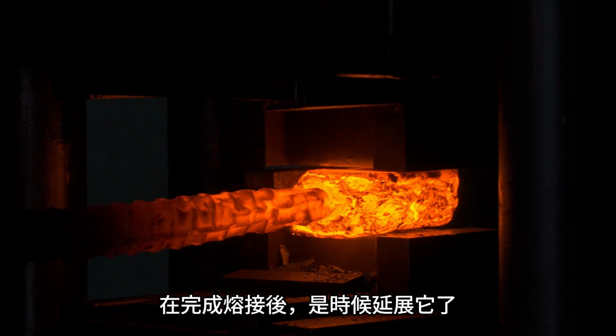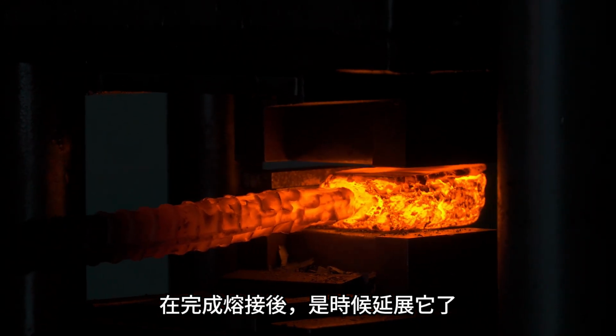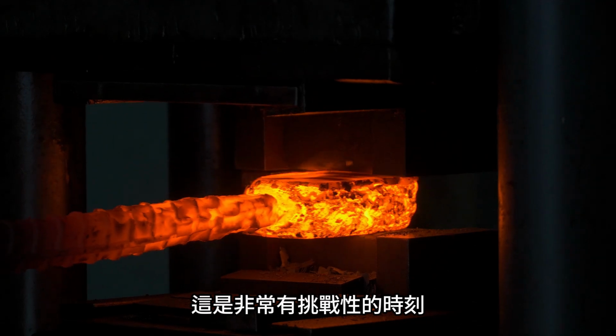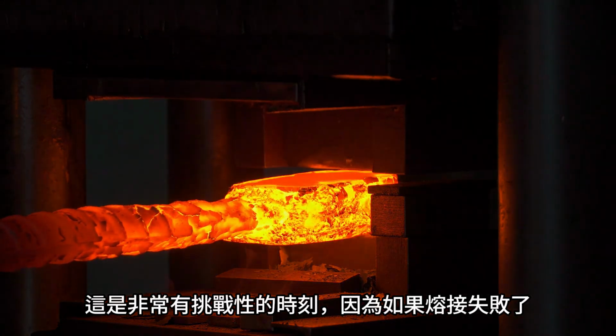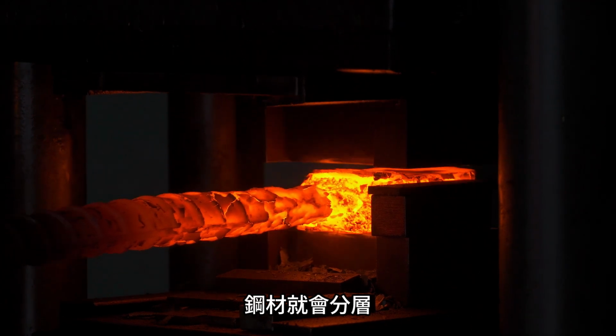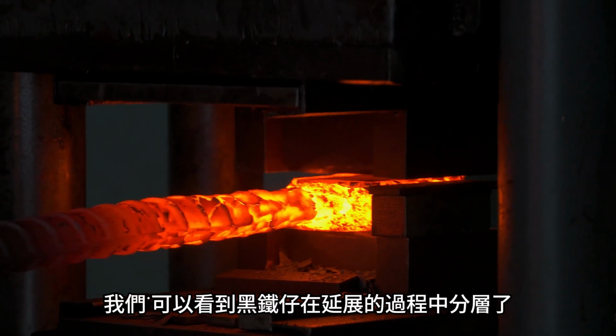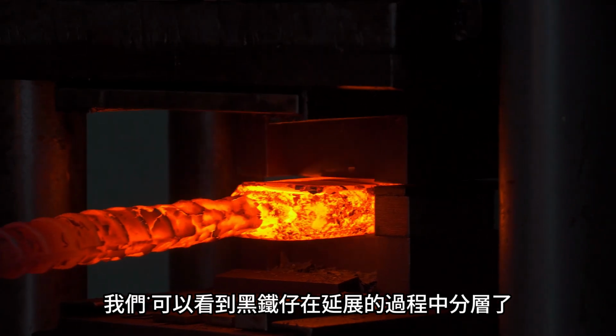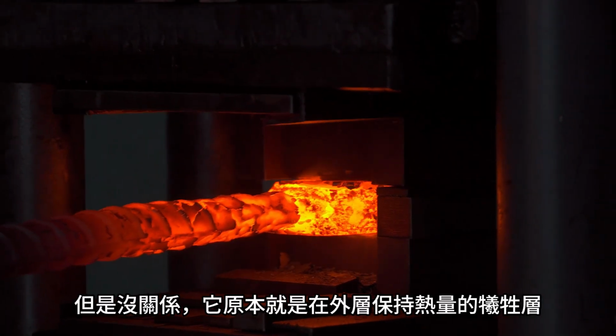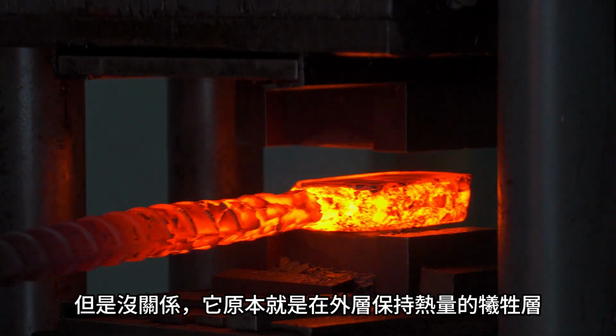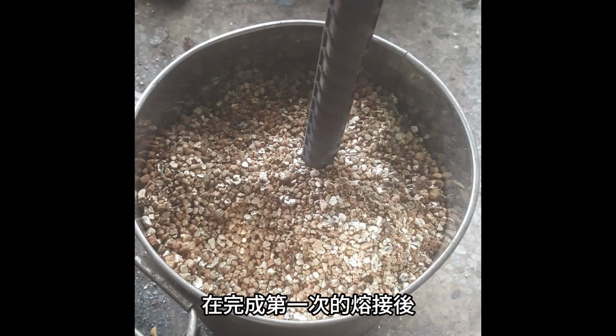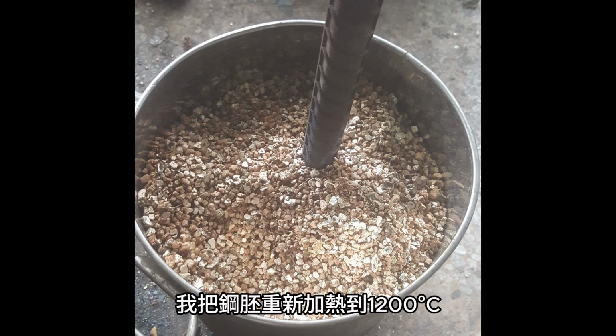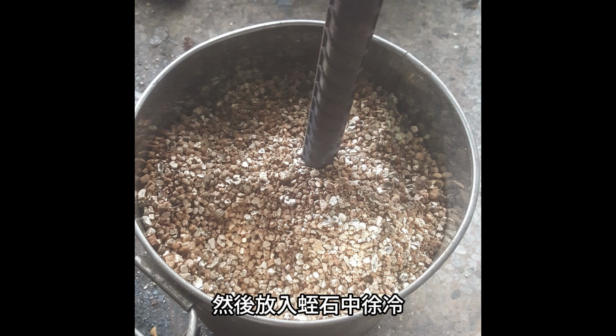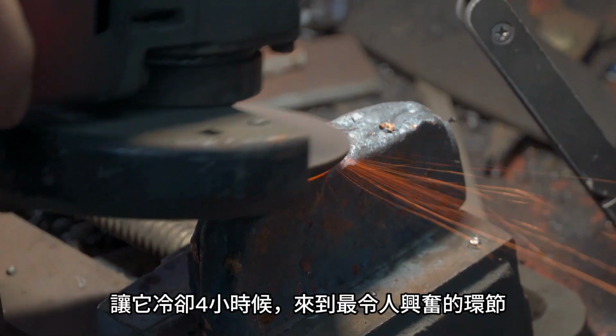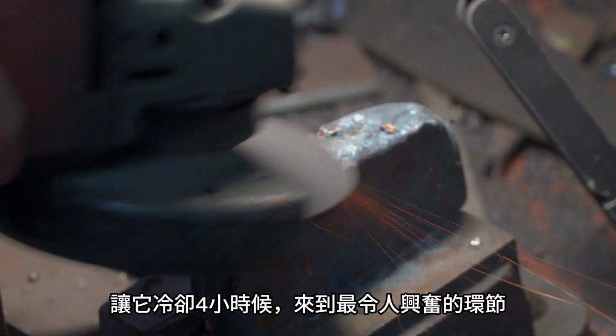After completing the forge welding, it's time to stretch it. This is a very challenging moment because if the welding fails, the layers will delaminate. We could see that the mild steel was beginning to delaminate during the stretching, but that's okay. It was originally intended to be an outer layer to retain heat. After completing the first forge welding, I reheat the billet to 2200 Fahrenheit and then press it in vermiculite to cool slowly. Letting it cool for 4 hours, the most exciting moment arrived.